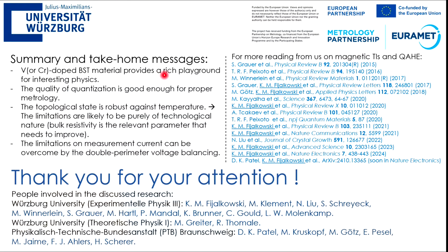OK, this would be it from my side, a couple of take-home messages. I hope I have shown you that vanadium or chromium-doped BST material provides a rich playground for some interesting physics. There's really a lot of topics I have not touched. The quality of quantization is good enough for proper metrology. The topological state is robust against temperature. So the limitations appear to be purely technological. So if we can make somehow the bulk more insulating, we should be able to build a standard at 4 kelvins. That's the bottom line. We have no idea how to do it, but at least in principle, it should be possible. There's nothing fundamentally preventing it from being doable.